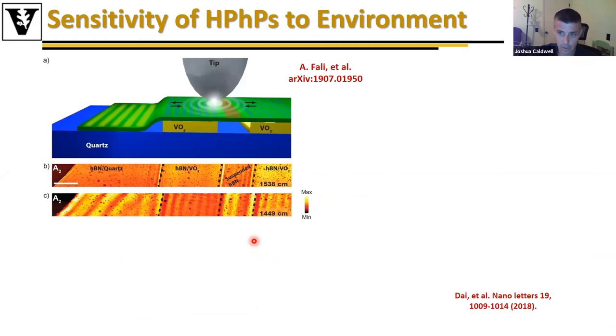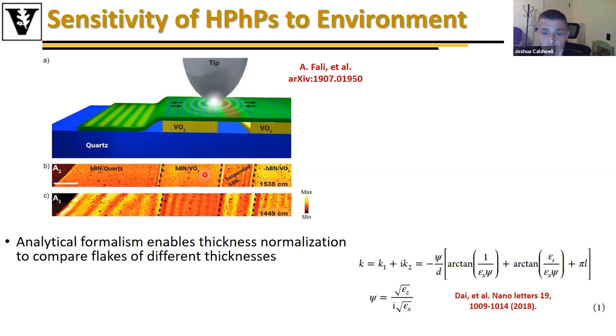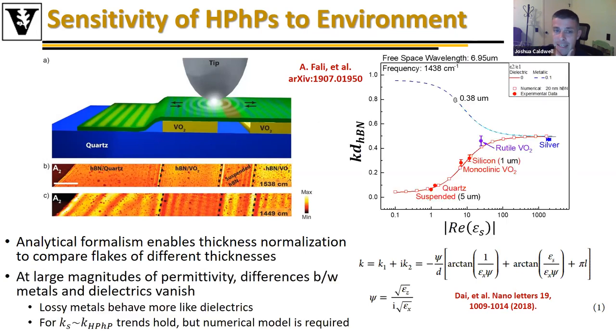And so we were able, in collaboration with Johannes Abade's group, to look at a broad variety of different substrates and determine what is the influence of the actual substrate upon this. And this is what's leading us to some of these on-chip photonic applications, right? Where now what we can do is take this analytical expression, which incorporates this substrate permittivity, and at a given frequency, look at how the polaritonic mode, the momentum of that mode, is modified by the underlying substrate. And you can normalize this to the thickness in this case. And thus I can see as I increase the dielectric permittivity that the momentum begins to saturate.